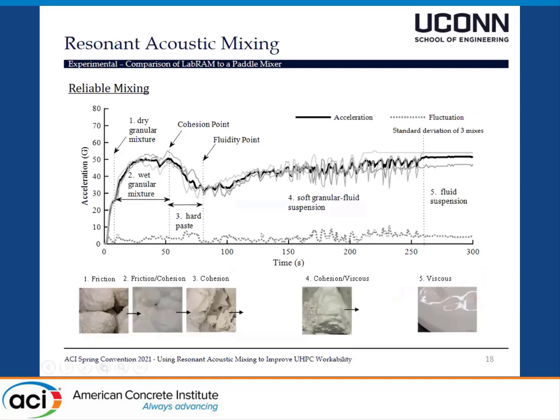If we take the fluctuation, which is the standard deviation of 3 mixes, we can pinpoint each time certain phases occur in the mixing regime. And where there is no fluctuation, we can see where the optimal mixing time is. The black line is the average, while the light gray is 3 of the different specimen samples. So we can definitely see that it does give reliable mixing results every single time.